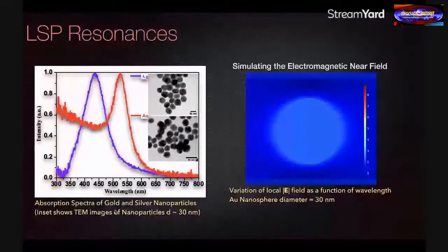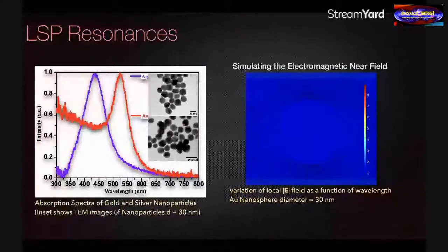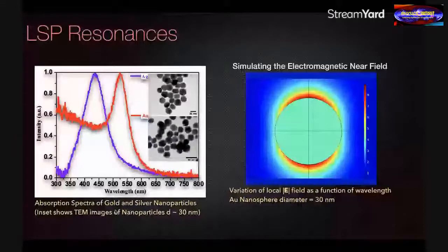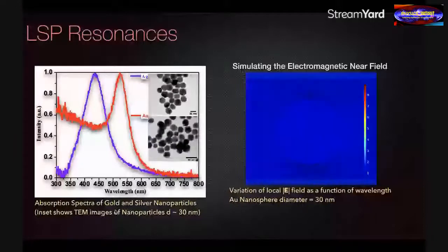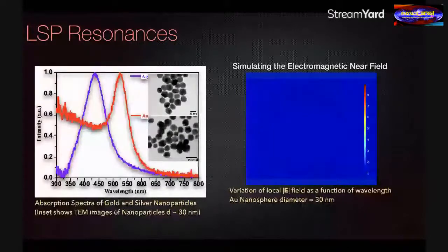If you look at it spectroscopically, the image on the left actually shows you an absorption spectra. So this light is actually absorbed and then re-radiated or scattered, as in the case. It gives rise to those brilliant colors that I showed you a couple of slides back, from very simple metal nanoparticles: gold, silver, copper, aluminium nanoparticles.